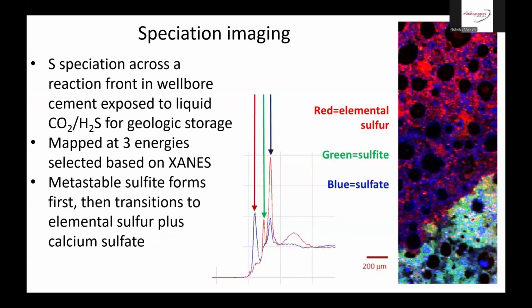A more local geologic example is the sulfur speciation across a reaction front in a wellbore cement. So it was a cement lining a well used for geologic storage of liquid CO2 mixed with H2S. And that was pumped down into the well as a geologic sequestration type of experiment. But it reacted with the cement, and we mapped at 3 energies, and then recalculated the relative contributions of each species. So the red is elemental sulfur, blue is sulfate, and green is sulfite. And the reaction front progressed from the upper left to the lower right.